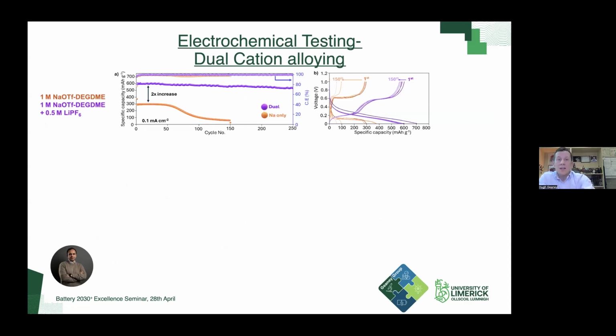So that was laying the groundwork for this dual cation alloying. What you'd see from this data are two sodium ion half cells, one of which, the orange one, is an NaOTF diglyme electrolyte, and the other is an NaOTF diglyme electrolyte that also has 0.5 molar LiPF6 in there. So we have essentially identical germanium electrodes, and we have a sodium counter electrode.